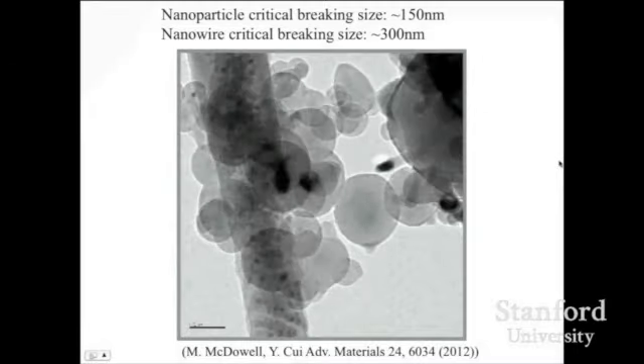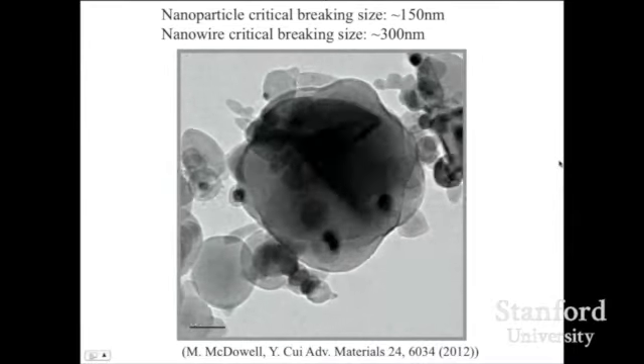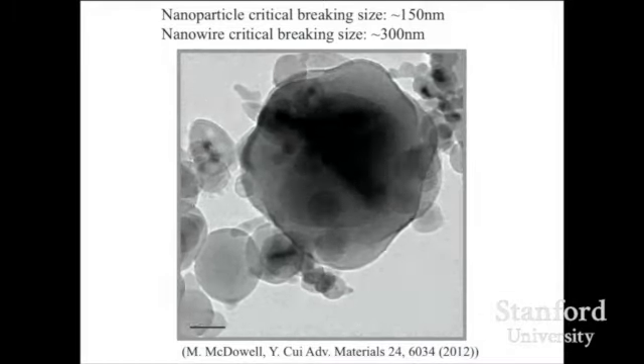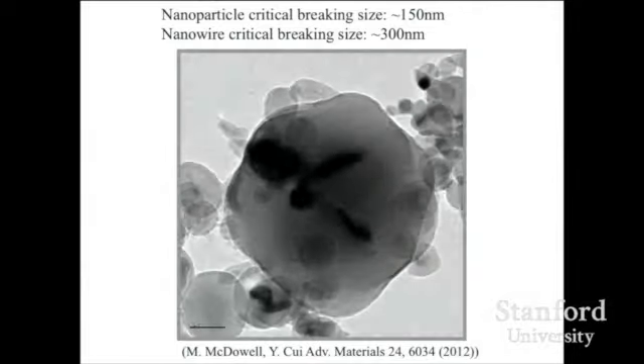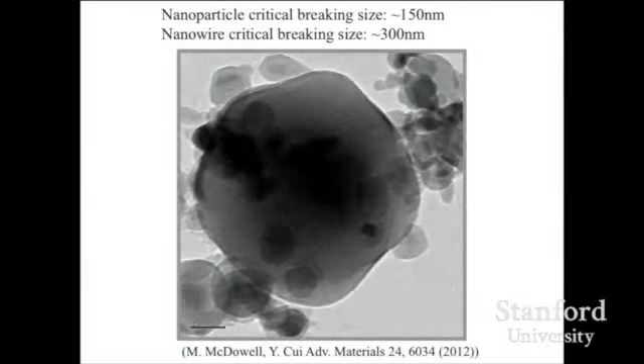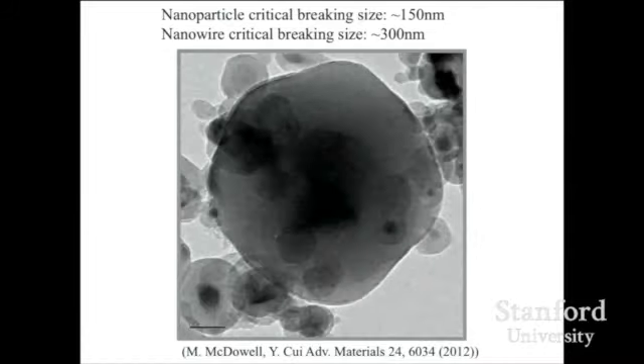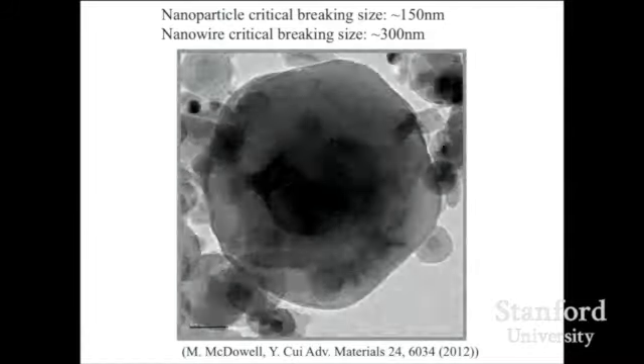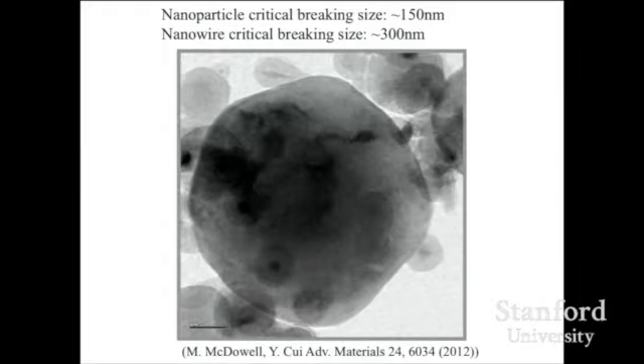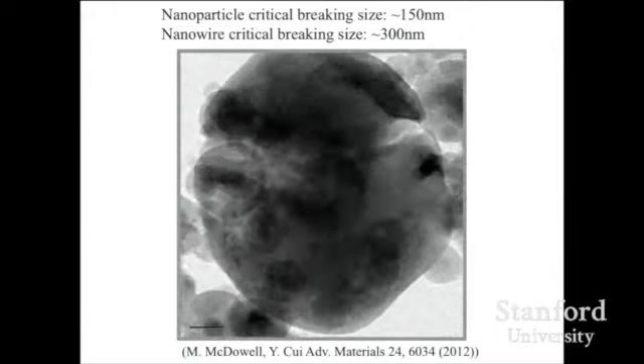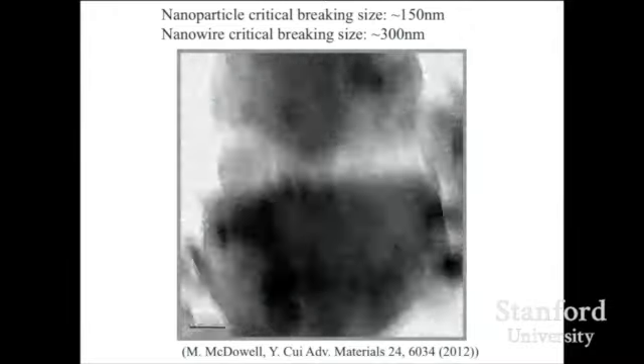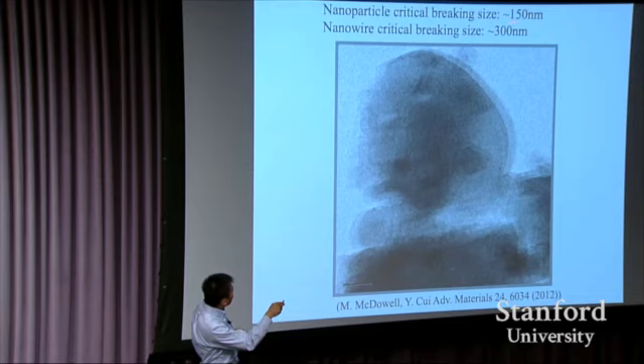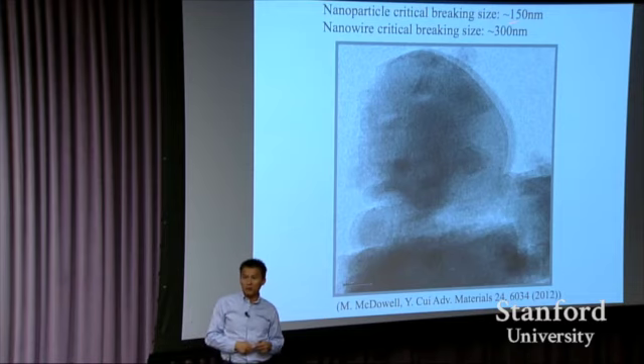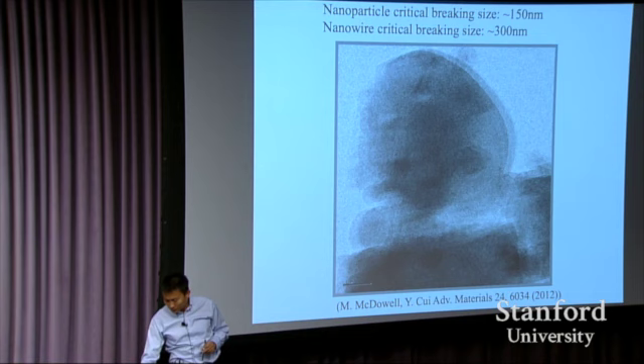Here we go. This is 200 nanometer scale, but this is a big guy, a big particle. Now you see lithium comes in, the crystalline silicon interface is shrinking. This is expanded. This particle is struggling because there's huge stress building up. At some point, it just cannot hold the stress anymore. You start to see it's going to pop open suddenly. Once this is popped open, game over, the battery dies. So now we also found out the critical breaking size for nanoparticles is 150 nanometers, and for nanowires 300 nanometers. We know what size to target in order not to have the breaking phenomenon.